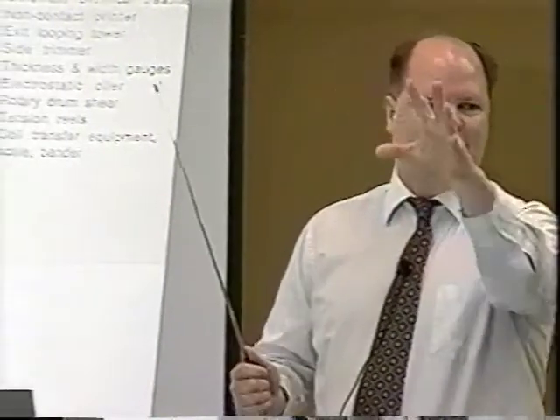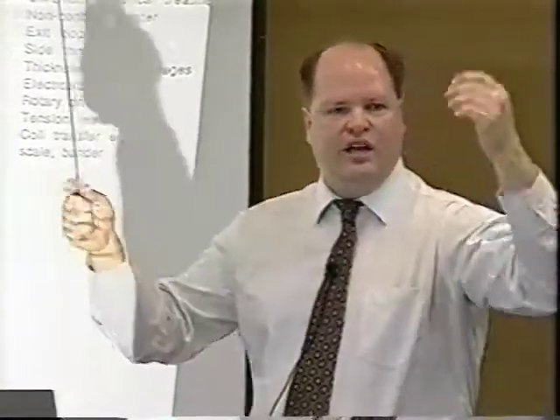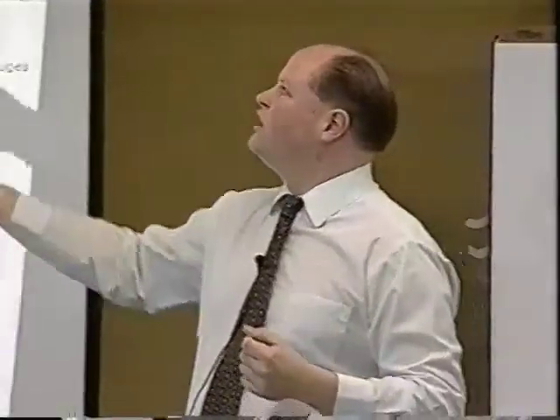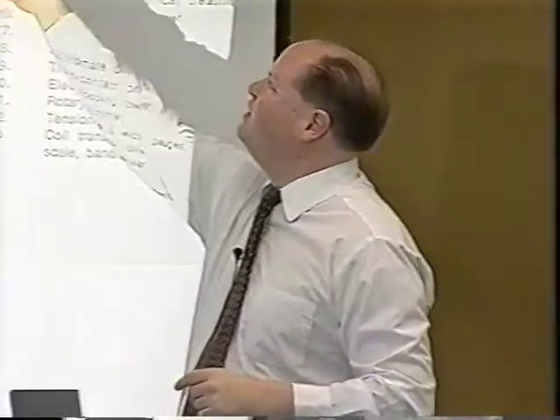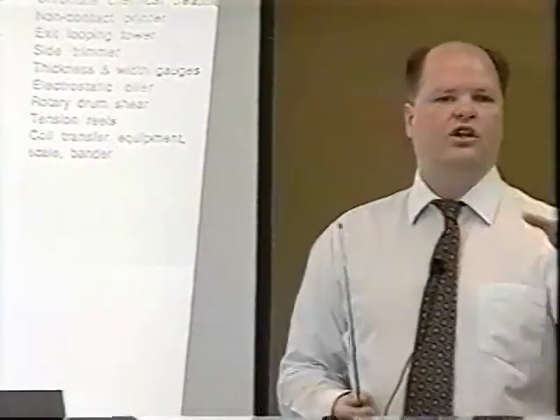galvannealing or under galvannealing. Under galvannealing is pretty easy to see because you won't have that galvanneal surface. You'll have little spots of galvanize on it, or you'll have edges that are galvanized. Over galvannealing is just as bad. If you heat it up too much, it may look okay. It's still that nice dull gray, but when you go to bend it, it's going to powder a lot more. If you heat it up too much, you're going to have a lot more powdering on galvanneal.